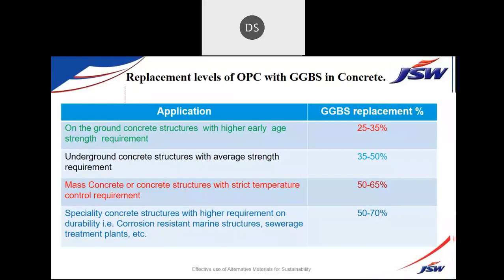This has been quite possible by using various chemical admixtures also. We specially designed the Fosroc Auramix range of admixtures, where we have added an accelerator. When we replace cement with GGBS, we need an accelerator supported by a retarding agent, and that should be a workable mix. So nowadays, concrete technologists are evolving many types of admixtures to meet the demand of the industry.